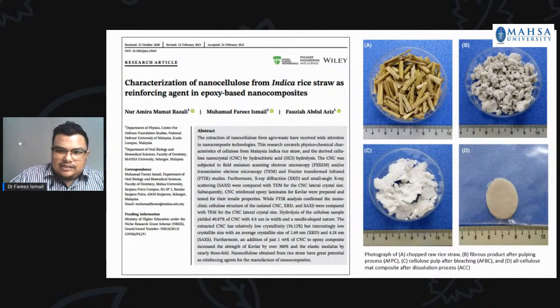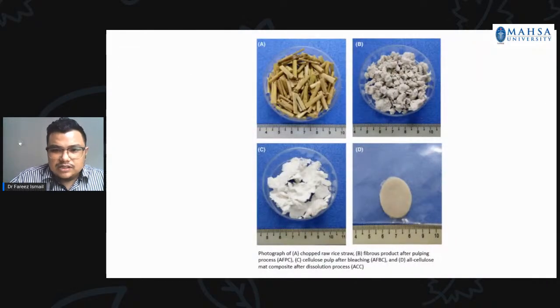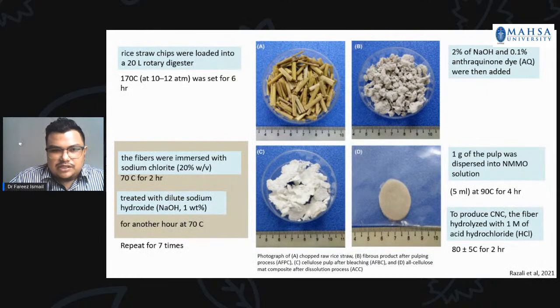And this is my latest research article published in Polymer Engineering and Science, where we isolated the nanocellulose, or cellulose nanocrystal, from indica rice straw. Let me just brief you how we did it. From the rice straw chips, it's loaded into the rotary digester, and then we add anthraquinone dye. Then we add sodium chlorite for the bleaching and sodium hydroxide. And this process we need to repeat 7 times.